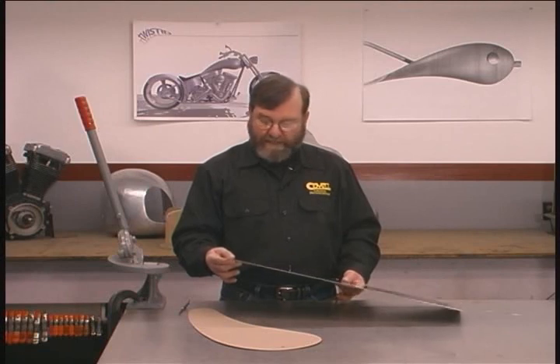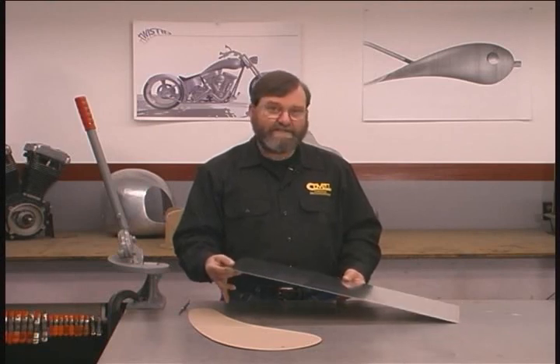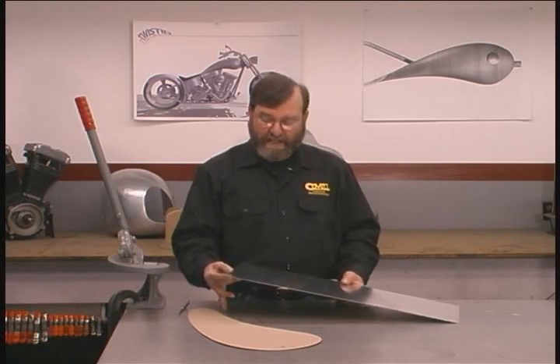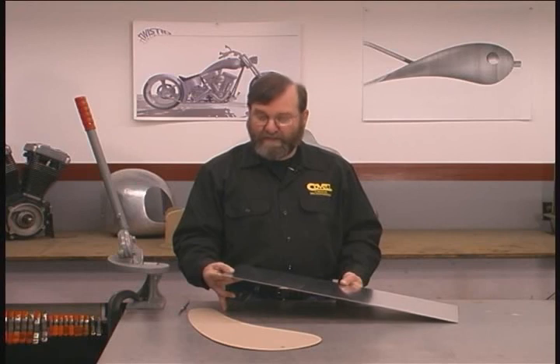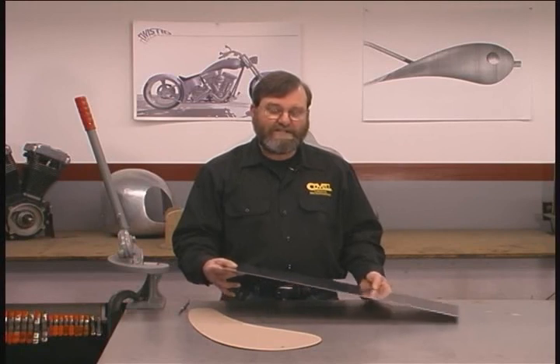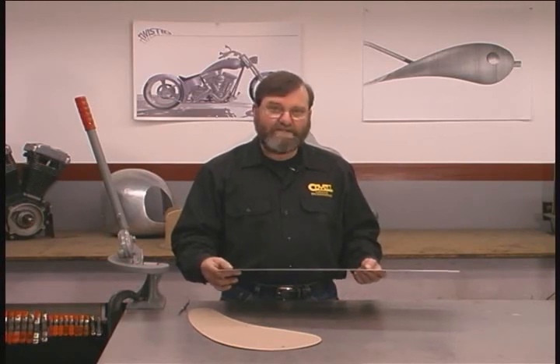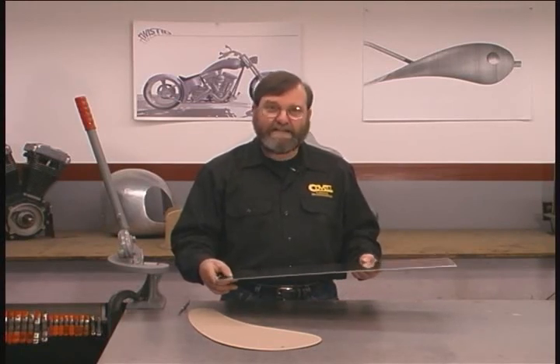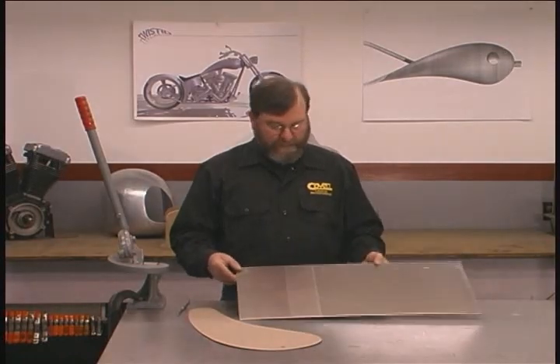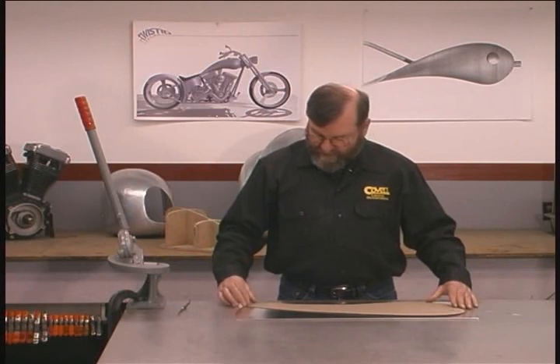This is a pretty good thickness to use for a motorcycle gas tank of this type. Some of the old English motorcycles use 60 thousandths aluminum for the gas tanks, and as long as they're very, very well mounted with a rubber cushion, that can work pretty well. But on motorcycles with V-twin engines that have a lot of vibration, especially with rigidly mounted engines, it's a lot better to use a thicker material. So that's why I've gone to 80 thousandths material. So we'll put the pattern on top of the metal, and we'll use a scriber to trace around the edge.